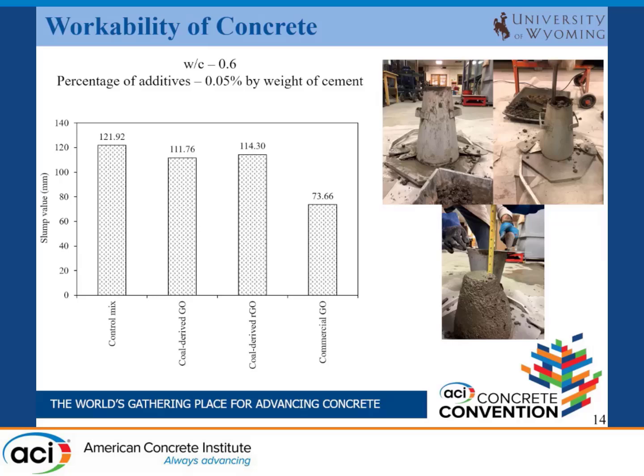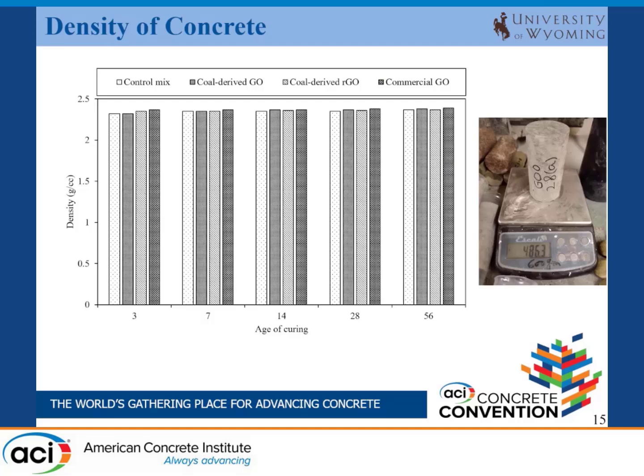We use our graphene oxide in the concrete at a percentage of 0.05% by weight of cement, and we keep our water cement ratio at 0.6. Whenever we introduce graphene oxide into the concrete, we saw in the workability that the slump value of the commercial graphene oxide decreases a lot more than our coal-derived graphene oxide and reduced graphene oxide. In terms of density of concrete, there is not much change between the 3 to 56 days age of curing.